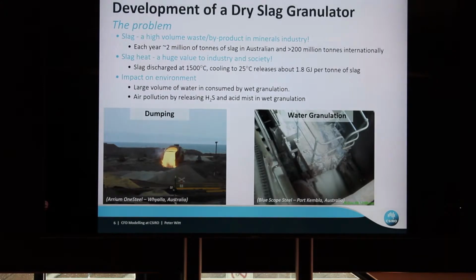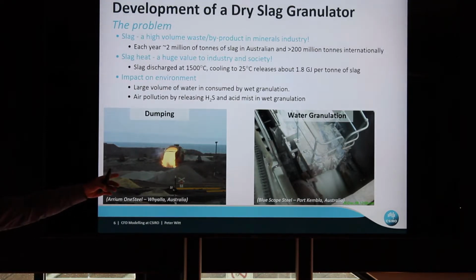So the problem I wanted to talk about today was development of a dry slag granulator. There's something like 2 million tonnes of slag generated by the steel industry in Australia and about 200 million tonnes internationally. It comes out at about 1500 degrees C, and as you can see by the picture, they either just dump it and let it cool, or they water granulate it. If you water granulate, you use a lot of water and produce a lot of H2S. If you just leave it and dump it, you've still got to do something with the material and you're losing a lot of heat.